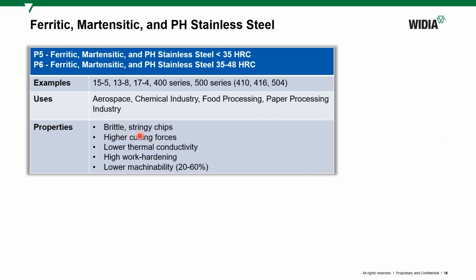In terms of properties, they're brittle and stringy, because martensitic stainless steels are hard. Because of the martensite phase, they are typically very highly abrasive and brittle, and require high cutting force, because hardness is directly related to the cutting forces. All stainless steels have lower thermal conductivity because iron is replaced by chromium and nickel, and they have a high work hardening nature. The low conductivity and high strength always lead to a lot of heat accumulation in the cutting zone, making the material subject to heat treatment and hardening. So they have a very poor machinability in the order of 20 to 60%. You can see that 20% is very low compared to 100% for a reference steel.